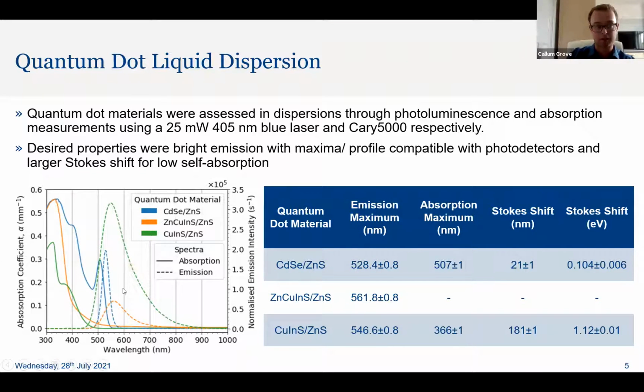The other thing to notice is that you have the absorption spectrum on this as well. There's a significant overlap with the cadmium selenium compared to the cadmium-free samples. A difference in absorption maximum and emission maximum produces a Stokes shift. So we have a 20 nanometer shift, or for those that prefer energy, 0.1 eV here, while the cadmium-free and very bright sample has a 181 nanometer or 1.1 eV Stokes shift.